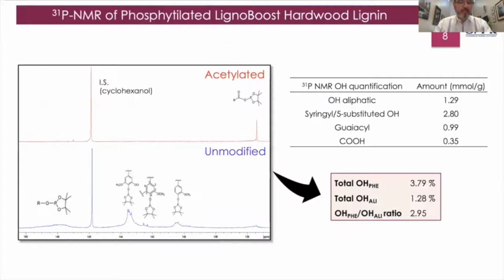This is the typical P31 NMR spectrum of lignin, in which one sees the quantitative analysis of different types of hydroxyl groups: aliphatic, syringyl plus 5-substituted hydroxyls, and this because the signals for the two are overlapping in the spectrum, guaiacyl hydroxyl groups, and also carboxylic hydroxyl groups. And these quantifications here shown provide the 2.95 ratio between phenolic and aliphatic that I've mentioned in the last slide.